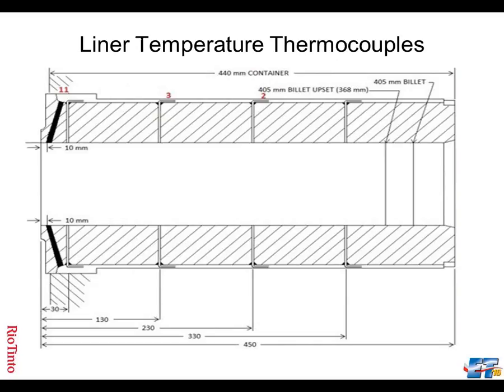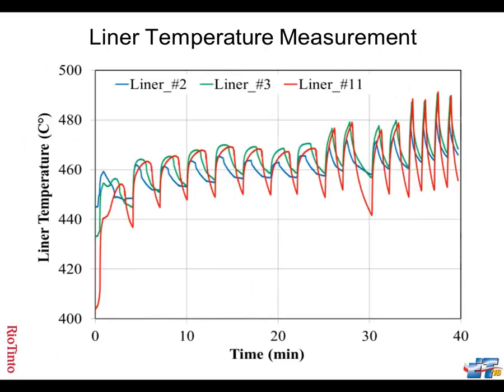First thing we measured was container temperature. On this press we have thermocouples located at the liner wall, so we can accurately measure the temperature of the billet as it extrudes. The kind of data we got was this. It shows the liner thermocouple varying over a 16-billet run: 4 billets to preheat, 4 billets at low speed, 4 at medium speed, and 4 at high speed. It shows the cycling. For the thermocouple located near the die end of the container, the temperature rise is something like from 450 to 490, 40 degrees Celsius. This data we can use to see how the model can predict this sort of information.